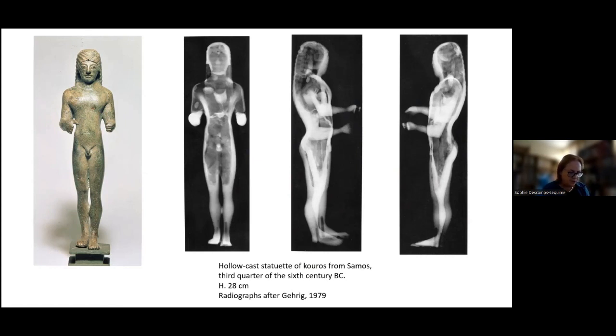Once adjusted, the two partial molds were removed, and the wax smoothed from the outside, the suture being more successful on the left than on the right, according to the different thickness of the bronze on radiographs. The thinning of the metal on either side of the chin would also provide evidence of sutures in the wax between head and neck.